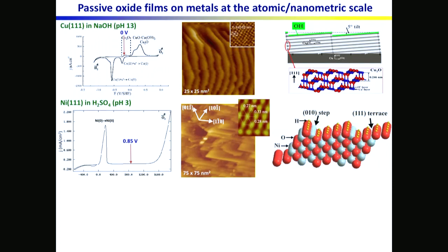And this is the polarization curve for nickel in this acidic solution, coming from slightly cathodic potential. You have a very high dissolution peak, so very fast corrosion, and above a certain potential, the current drops, and this corresponds to the formation of an oxide on the surface. And clearly, this oxide is protective because the current decreases a lot, and there is only a small remaining current in what is called the passive region for this metal.